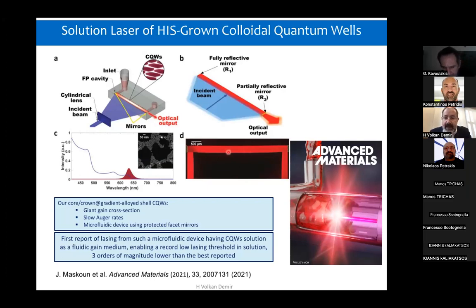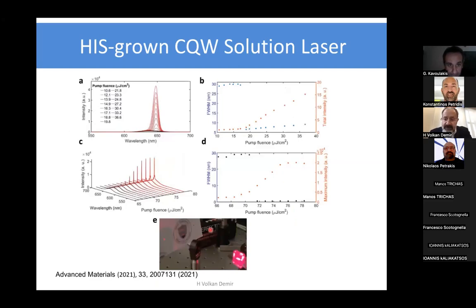And this channel has only the core crown gradient alloyed shell. This shell actually has hot injection growth, as we would like. And with this type of solution-based medium, it's very difficult to induce gain at reasonably low thresholds. However, if the gain material itself has a high gain coefficient, as should be for this specific, highly engineered colloidal quantum well, it is possible to reduce that threshold. And this is what we observed ourselves. This type of colloidal quantum well gave us a threshold which is 3 orders of magnitude lower than the best reported values in the literature. This includes previously the colloidal quantum dots, the dyes, and a variety of soft material options and molecules. This is really truly coming from the material itself. One can look further into the details of their lasing behavior.